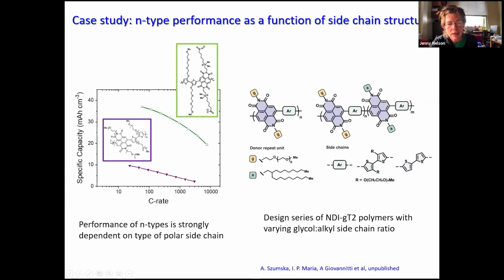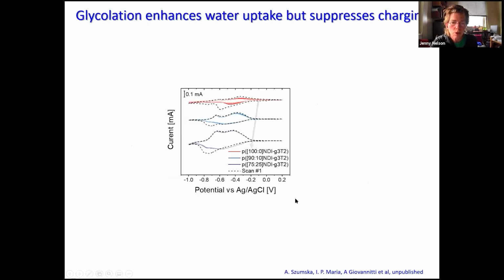We took this fully glycolated polymer and then replaced some of the side chains on the NDI with alkyl side chains instead of glycol side chains. And we then studied the performance as a function of that ratio of glycol to alkyl side chains. So first of all, we show you the CV properties.